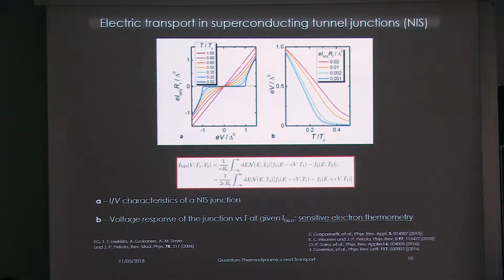From this we see that it is very important. The characteristic of an NIS junction basically depends only on the electronic temperature of the normal metal reservoir, at sufficiently low temperature, not on the temperature of the superconductor. What is nice is that as a function of temperature you can have very sharp features, with a very rapid slope.